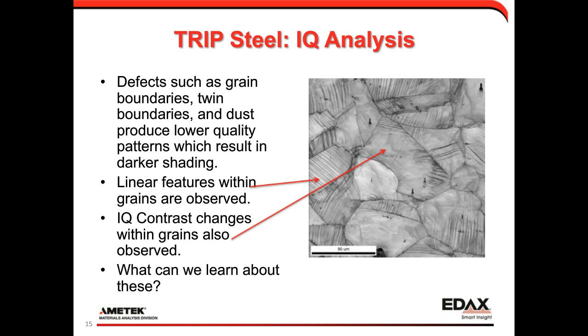If we look at a TRIP steel example with the IQ map, we see that the contrast in that map shows quite a few different microstructural features. We see grain boundaries, we see twin boundaries. We can also see little pieces of dust where the pattern is not shown completely and it turns out a little bit darker. We see linear features. We see contrast changes within the grains. So the next question to ask is, what can we learn about these different features using EBSD?